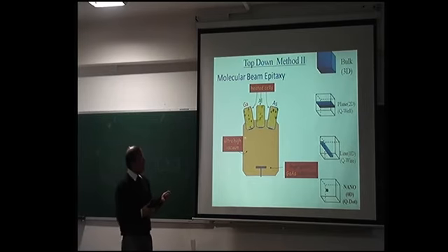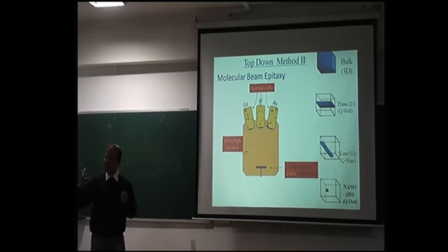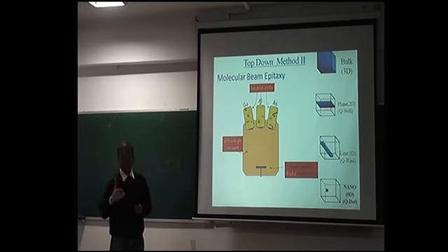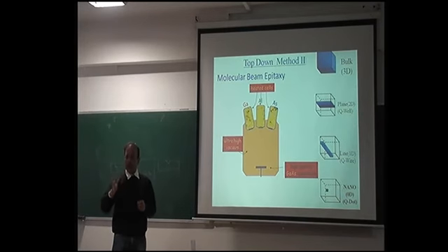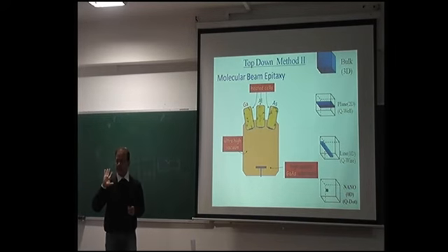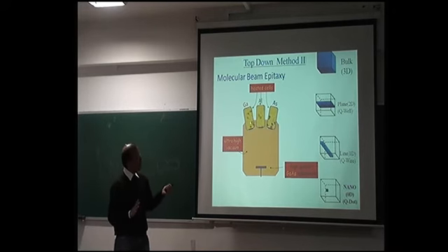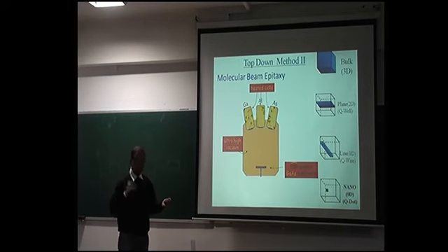As I said, you take gallium aluminum arsenide. This is technically called a diffusion cell. It is nothing but a metallic chamber where you have this metal either in liquid state or solid state, and you heat this chamber to more than the melting point, typically 200 degrees centigrade more than the melting point of that particular solid. Keep the system overnight. Go to vacuum 10 to the power minus 11 is better, but at least 10 to the power minus 10.